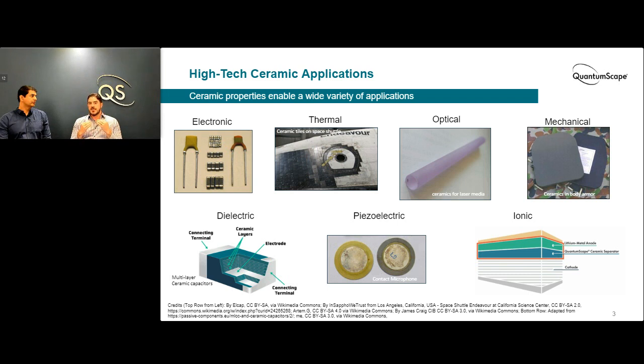It involves making very thin layers of ceramic material on the order of about 1 micron thick, which, in contrast to what QuantumScape does today, is very, very thin. Our layers of ceramic are 20 microns to 40 microns. The MLCC industry has been making layers on the order of 1 or 2 microns now for years. So it's a very advanced, high-tech application of ceramics to make a relatively low-cost part. And ceramic capacitors are made in the billions of parts per year, and they only cost a few cents.